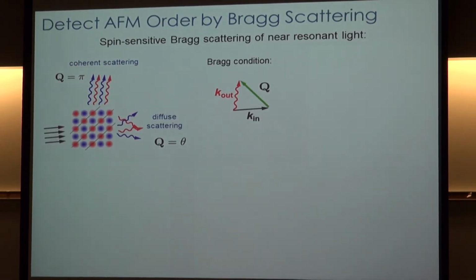So now I want to get to the heart of the experiment. This is what I really want to tell you about today during this talk. Everything else is kind of a warm-up. So we're taking a page from the condensed matter experimentalists to detect magnetism by doing Bragg scattering. You probably know about X-ray scattering off of crystals, X-ray crystallography, to measure crystal structure and lattice spacings and so on, or neutron scattering, which is sensitive to spin. And then we're doing light scattering, but also in a spin-sensitive way. And so you can see here that if you have antiferromagnetic order, you have certain symmetry planes.